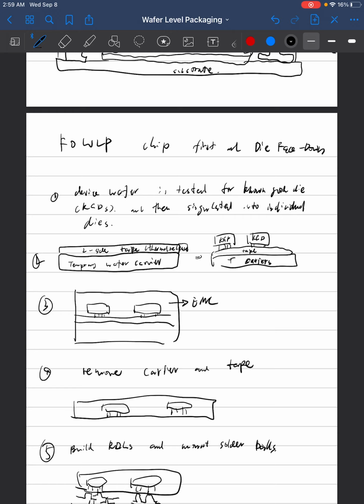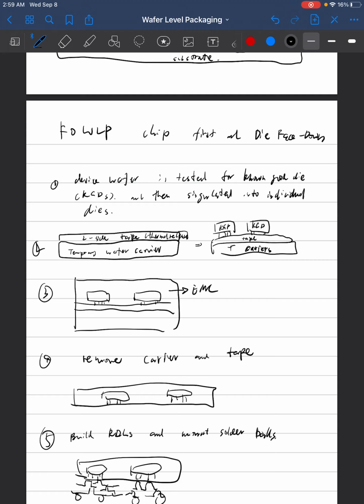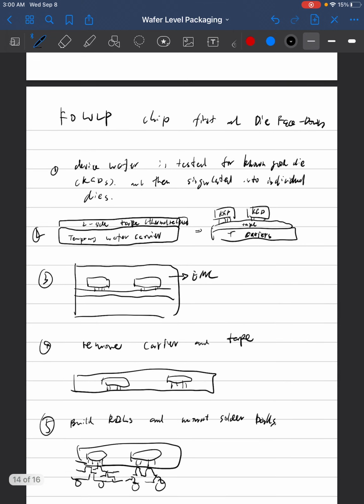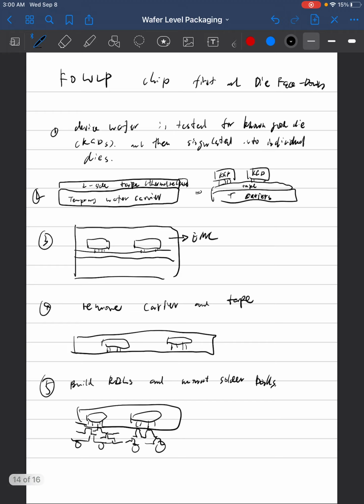In the chip first method, there are also two types. One is chip first, die facing down, and the other is chip first, die facing up. The general process for the chip first, die facing down is shown below. First, the device wafer needs to be tested for KGD, known good dies, then singulated into individual dies. After that, we put the known good dies facing down onto two-side thermal release tape on temporary wafer carriers. Then the whole known good die on the temporary wafer carrier is molded with EMC, epoxy molding compound.